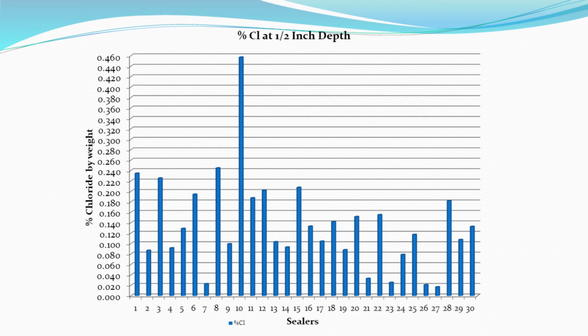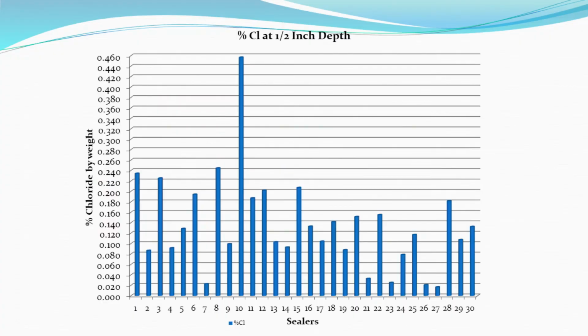You can see that many of the systems are probably 0.1, 0.08, 0.1 chloride by weight percent concrete at 1/2 inch in 90 days. So the very low bars there, that's obviously the couple, 4 systems of penetrant sealers that gave you a high percent reduction in chloride ion penetration.